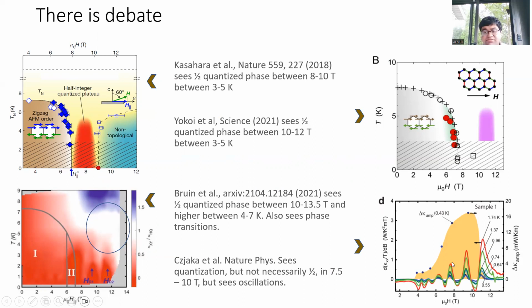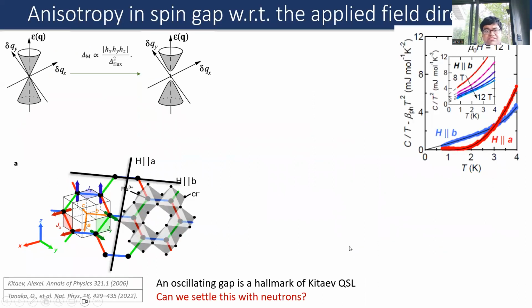Then some of our own measurements with the Princeton group did not see the quantized Hall plateau in some of our samples, which were grown using the CVT method, which is different from the Bridgman technique that they are using to grow their samples. So there is a lot of sample dependence here, where we saw these nice quantum oscillations, which looked very much like Shubnikov-de Haas type oscillations.